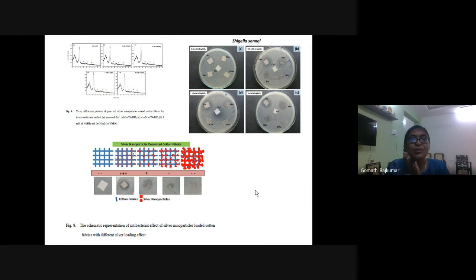So this was the silver loading capacity. And guys, something else I could tell you is that it was durable even up to 30 washes. When we washed these cotton fabrics, we could see the presence of silver oxide nanoparticles and the durability of these silver nanoparticles on the cotton fabric. They lasted for 30 washes. So the durability is around 30 washes.